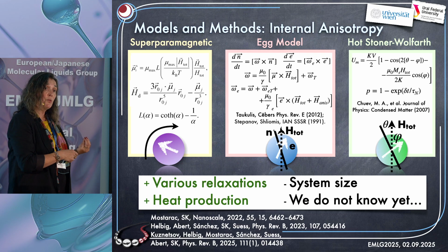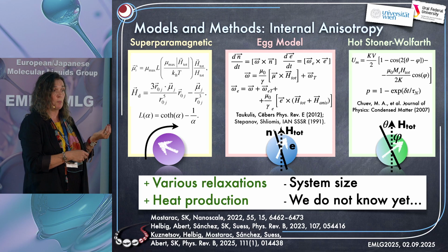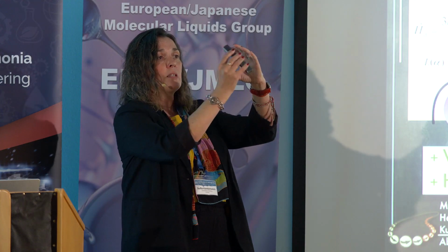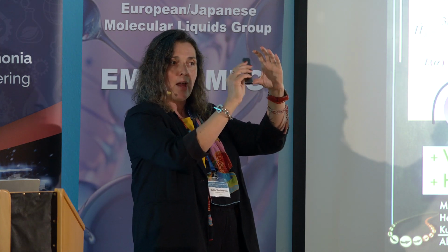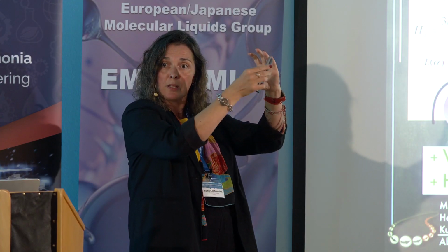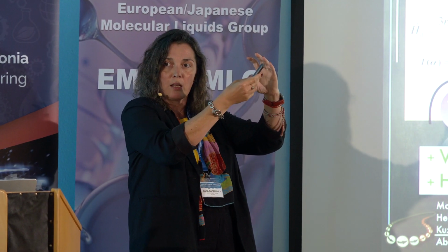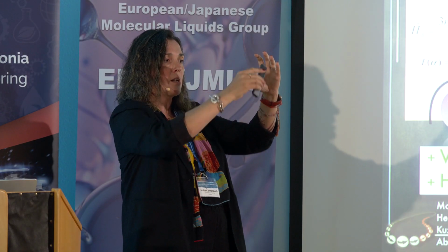When the particles are not that anisotropic, you don't expect the two-state model to work properly. Instead of being either here or here, the magnetization can actually precess around the easy axis. This is its own frequency of oscillations that has to be taken into account. And then it can also point outwards of the easy axis.